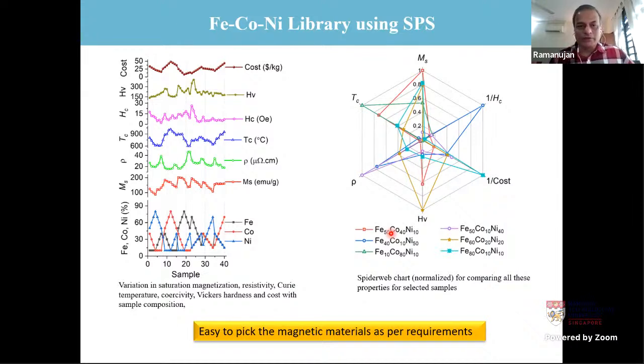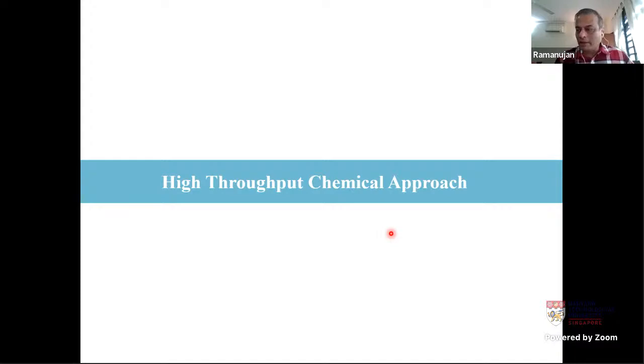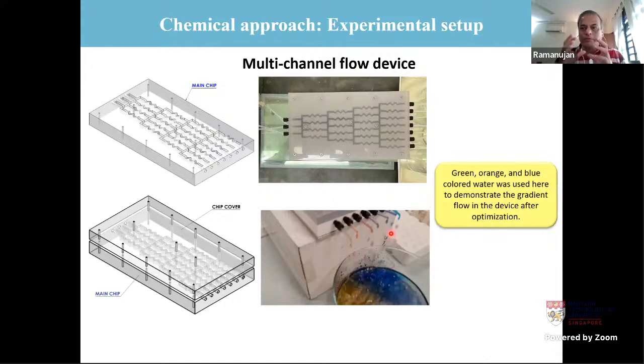So this was using spark plasma sintering. We also use chemical synthesis. So I'll go through this. We've developed multi-channel flow devices, which you can see here. Using these multi-channel flow devices, we can mix precursors. In this case, we start with three iron, cobalt, nickel precursors, and they get mixed in various ratios here. And you can get, in this case, 7 outputs with different colors. So by this method, we can actually create a whole range of compositions readily. Just by chemical methods, in this case, we're lucky because iron chloride, nickel chloride, and cobalt chloride are easily reducible. So you can perform a chemical reaction within this device and produce the requisite magnetic nanomaterial powder.